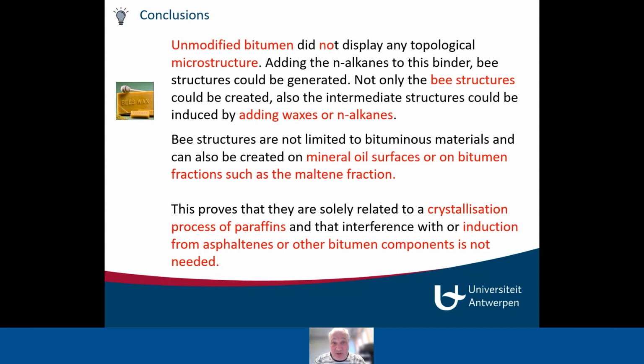You see that unmodified bitumen, or bitumen without wax, is not showing any microstructure. For us, it's very clear that these microstructures, these bee structures, are formed by a combination of different n-alkanes. So different chain lengths will result in these bee structures, and we can correlate certain chain lengths and certain combinations to certain morphologies and certain distributions of bees. And then we also see that we can generate bees in oil or in paraffinic oil. So there is no interference of asphaltenes or other bitumen components needed. So it's clearly due to the crystallization of the paraffins.